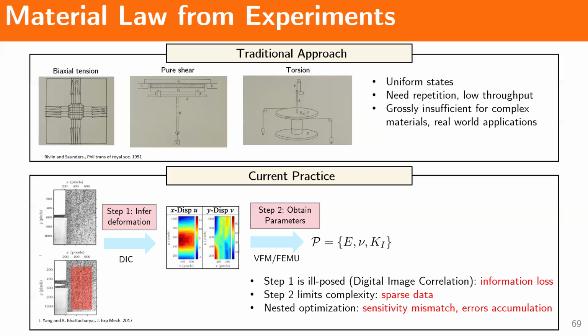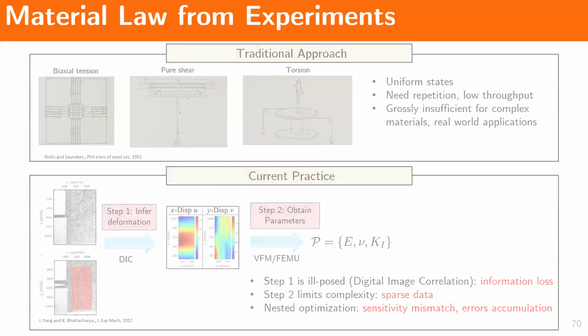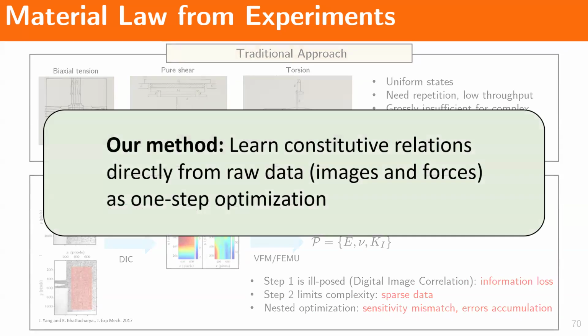And then of course you run into issues with any nested optimization technique, where you have sensitivity mismatch between step 1 and step 2, or you can also have error accumulation through this entire process, right? Okay, so now we're going to propose a method where we can learn constitutive relations, a constitutive model, directly from the raw experimental images as a one-step method. So we're not considering these two steps anymore. And in doing so, we're trying to avoid all the limitations that we've seen that are associated with the two-step approach that traditionally people are doing.